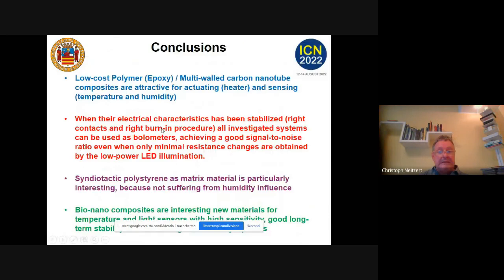Okay, what can we say? Low-cost polymer epoxy multi-walled carbon nanotube composites are attractive for actuating and sensing. They can sense temperature and humidity. I would say, because all sensors should be specific to one would be nice, they are specific to two, of course. When their electrical characteristic has been stabilized, with the right contacts and right burn-in procedure, all investigated systems can be used as bolometers, achieving very good signal-to-noise ratio, even when only minimal resistance changes are obtained by low-power LED illumination.